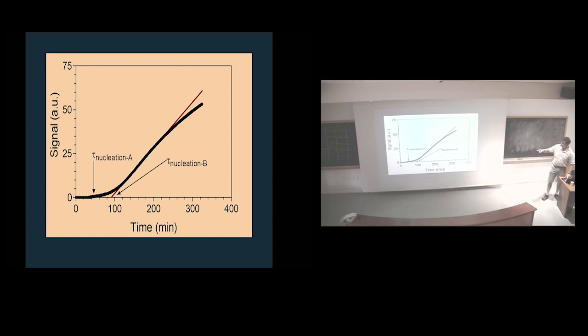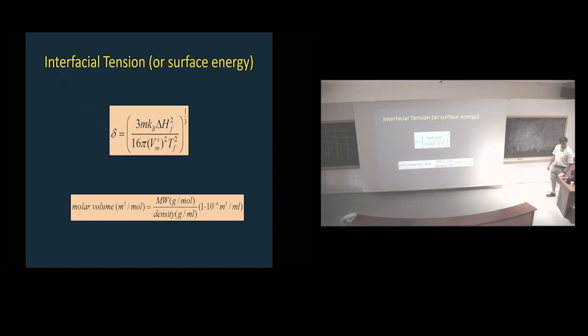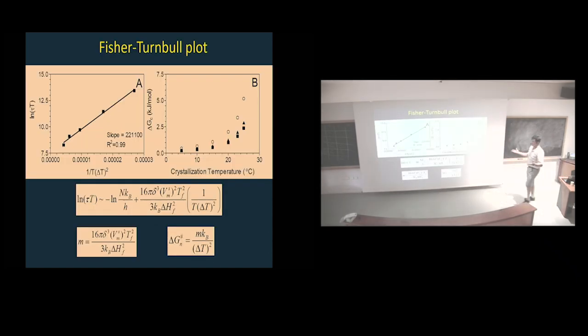And so what do you do with that induction time of nucleation, right? It's up to you. I'm not going to get into whether you throw a line here and call that the induction of nucleation, or you say it's the departure from the baseline. I'm too old for those discussions. You can report both so that people cannot yell at you too much. Then this is the Fisher-Turnbull plot, the classic Fisher-Turnbull plot. All I did is take that equation, remember the equation?